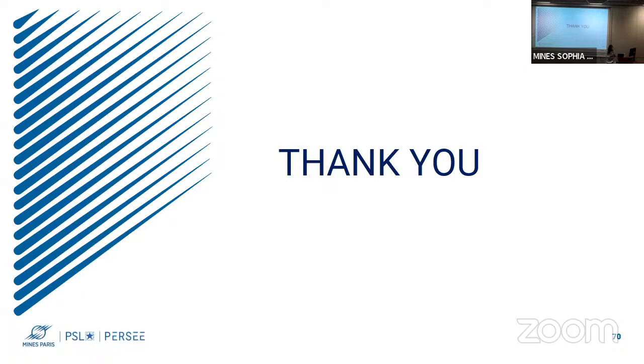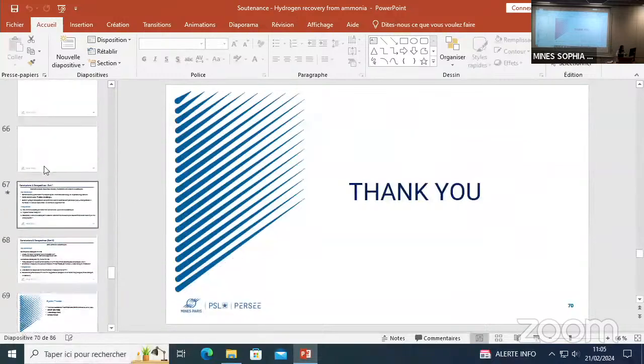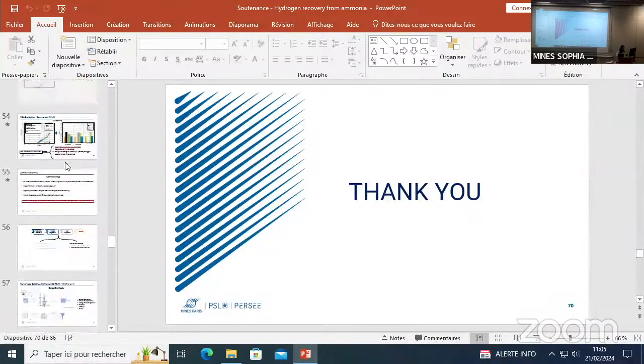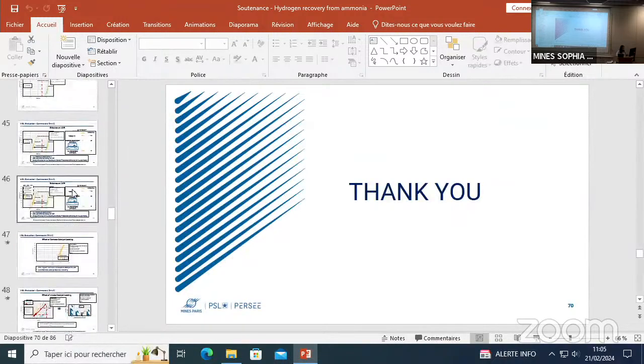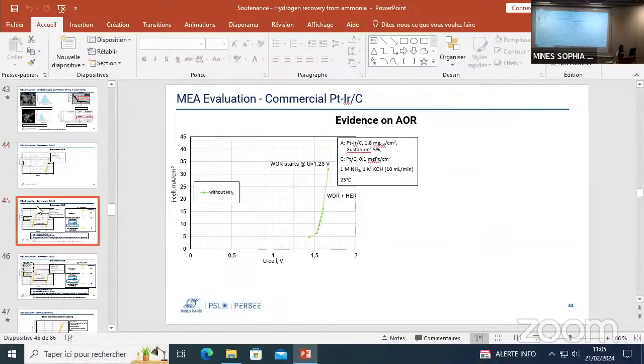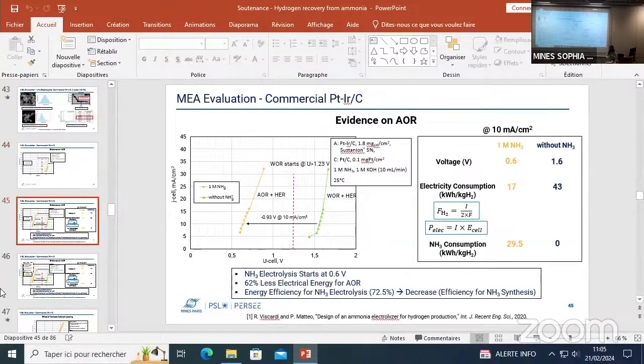During my tests, for example, if we go to, I don't remember where. First, when I tried to give evidence on the ammonia oxidation reaction. In this slide specifically, we could see that this is in the absence of ammonia, so this is completely the water electrolysis reaction. And this is in the presence of ammonia. And you can see that theoretically the water oxidation reaction starts at around here, but practically it starts here. So throughout the whole range of the test, when I have ammonia, I'm only producing hydrogen from ammonia electrolysis.